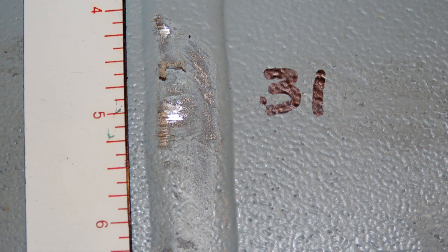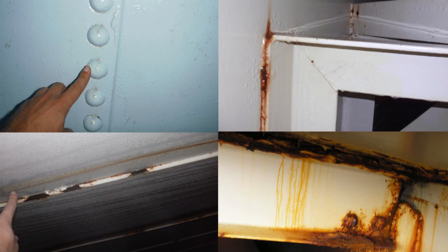Pinholes are usually caused by poor wetting of the coating or lining on the surface during application, poor application practices, or outgassing of air or solvent without subsequent flow out of the coating. Holidays and pinholes are commonly found on areas that are difficult to protect or access, such as edges and corners, welds, bolts, nuts, and threads, behind angles and clips, between back-to-back angles, etc. Large flat surfaces like walls of a tank or vessel are easier to coat and therefore usually contain fewer pinholes and holidays.